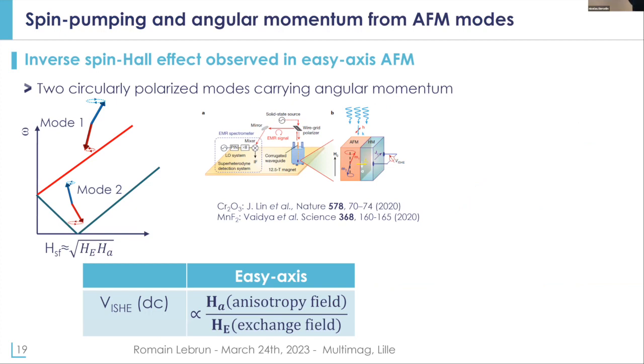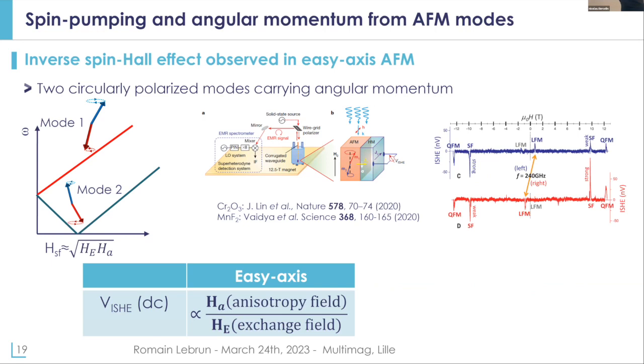The key question is: what can be the amplitude of this electrical signal we can detect in the case of an antiferromagnet? Inductive detection is quite difficult with an antiferromagnet because you have a compensated antiferromagnetic order — the inductive signal is extremely small. This is why we try to detect magnetization dynamics via the inverse spin Hall effect. Two nice papers published about three years ago detected this inverse spin Hall signal when exciting the antiferromagnetic resonance, applying very high magnetic fields and generating frequencies at a few hundred GHz. The detected signals were extremely small, about a few nanovolts.